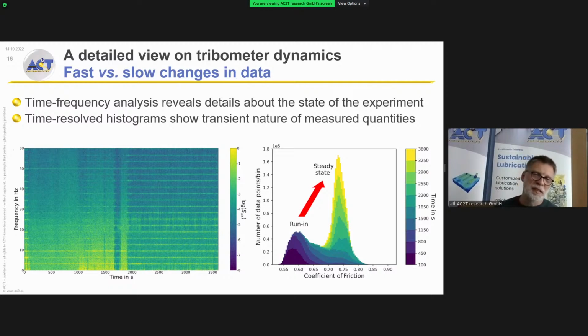On the other hand, on a cycle resolved or time resolved basis, you can see how the system evolves over time. Tribological testing is always combined with some run-in period where the two surfaces have to adapt to each other, and then go to some state where the system behaves stably, and normally this is accompanied by a change in the friction force, for example. So this is all classical conventional data analysis, I would say, and it is very powerful to understand what's going on in the experiment and to help you get clean data.